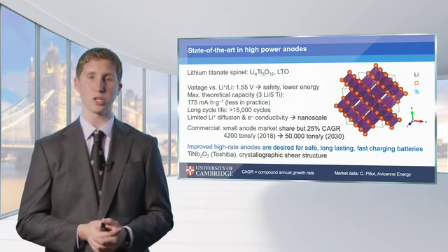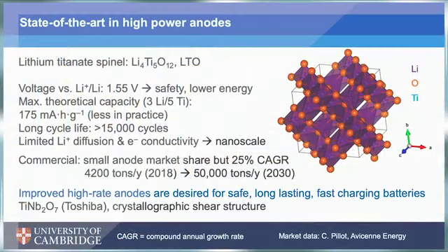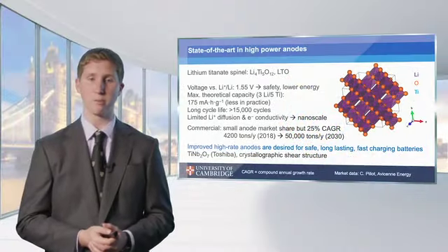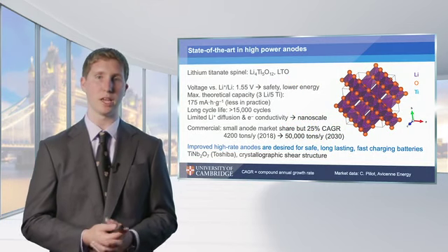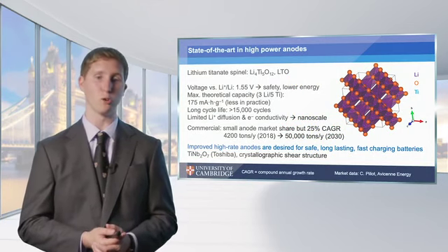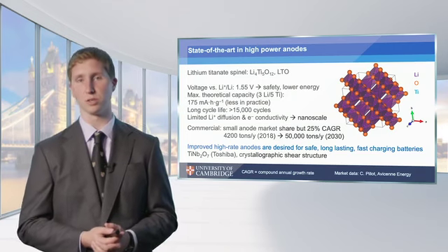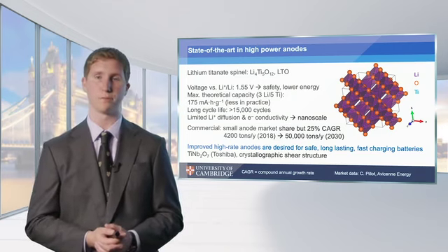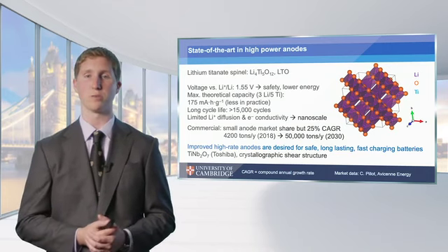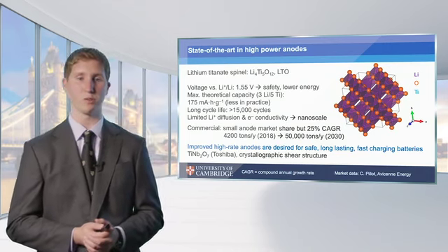Even though the market share of this is small, at around 4,000 tons a year and say 3 or 4% of the market, it's growing very rapidly because there is an increasing demand for fast charging applications and high power batteries. We're seeing a 25% growth every year and expecting 50,000 tons in just about a decade of these high rate anodes. So there's clearly a demand for high rate anodes, and it would be even larger for new materials that have advantages in terms of energy density or temperature operating conditions, or one of the other variables that can exceed the performance we have now for fast charging batteries.